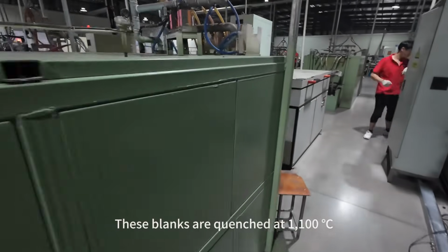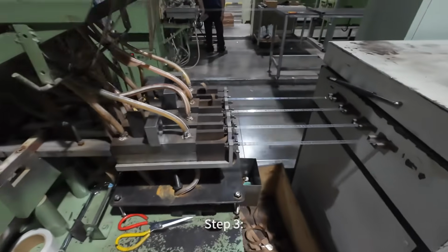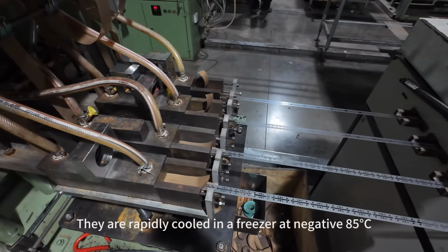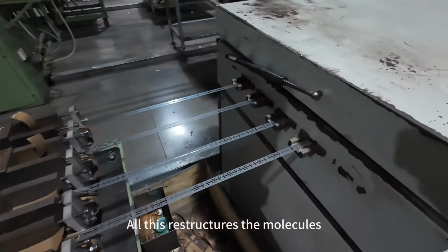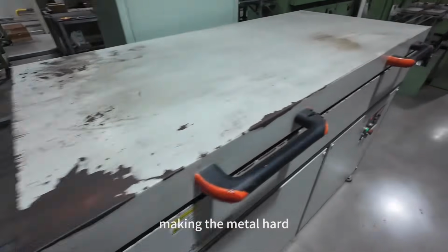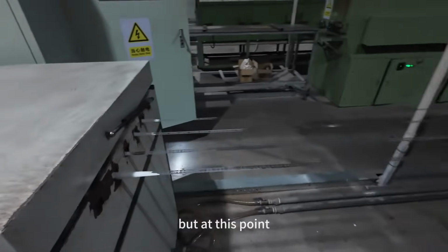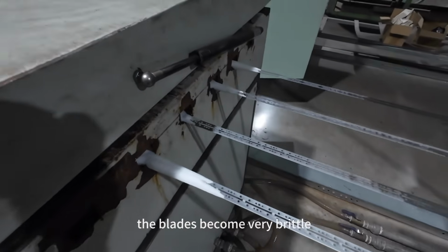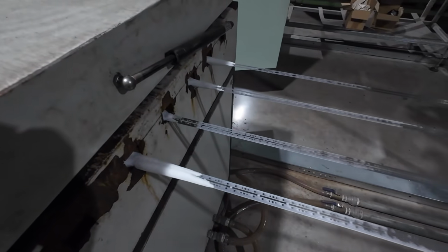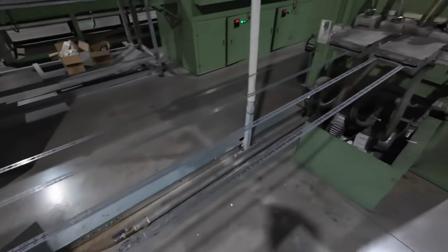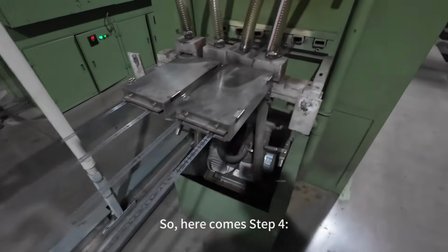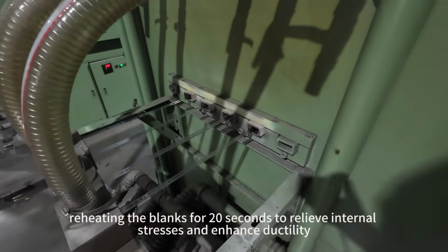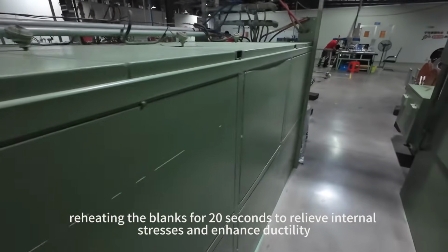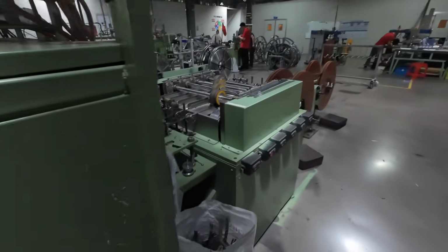1100 Celsius. Step 3. They are rapidly cooled in a freezer at -85 Celsius. All this restructures the molecules, making the metal hard, but at this point the blades become very brittle. So here comes step 4. Reheating the blanks for 20 seconds to relieve internal stresses and enhance ductility.